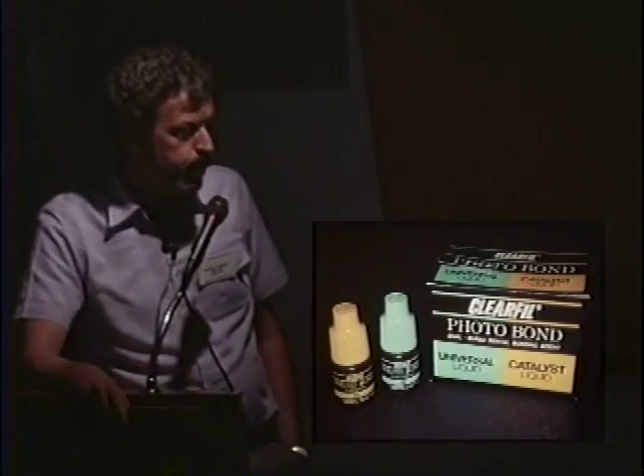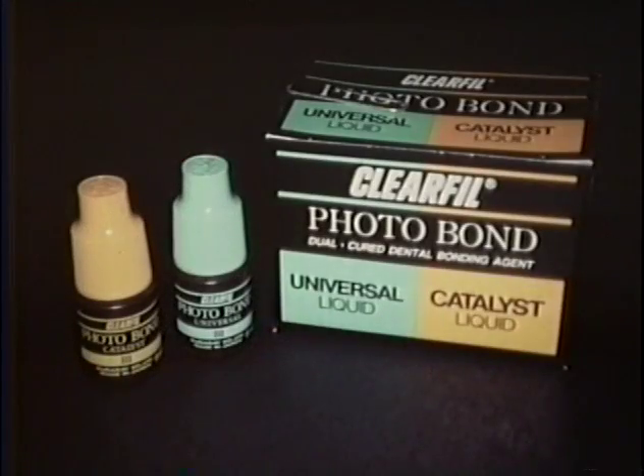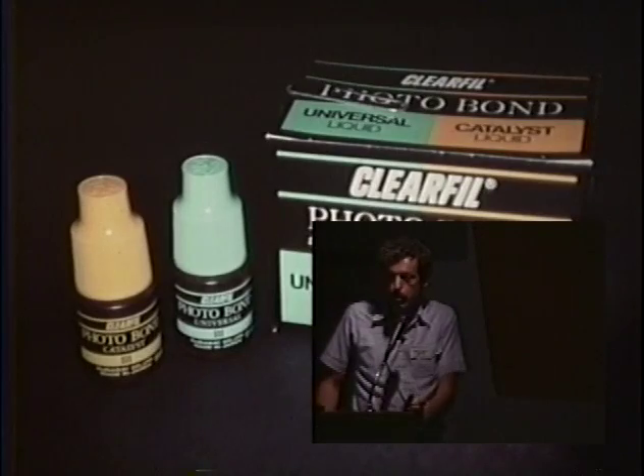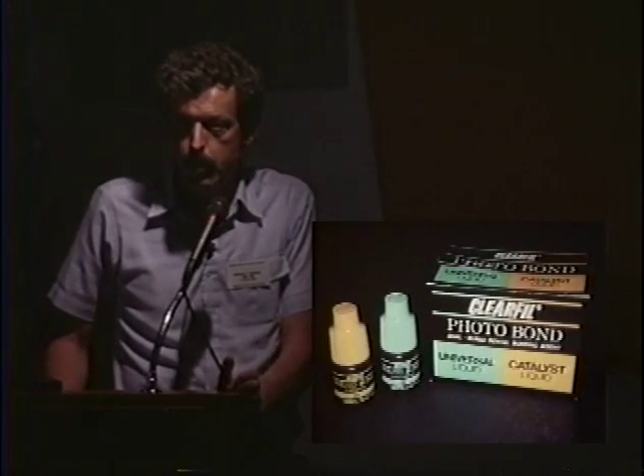Now the catalyst in Photobond there is a very unique one. It's one that's really very active. And one of the secrets of why Photobond bonds dentin so well is in fact this catalyst here really polymerizes the material very well. So what happens is you put the Photobond on the dentin and enamel and you have a surface scum there that's air inhibited like most bonding agents are. And that air inhibited scum then is liquid even after you cured the material, just like most of the BIS-GMA bonding agents that everybody knows.